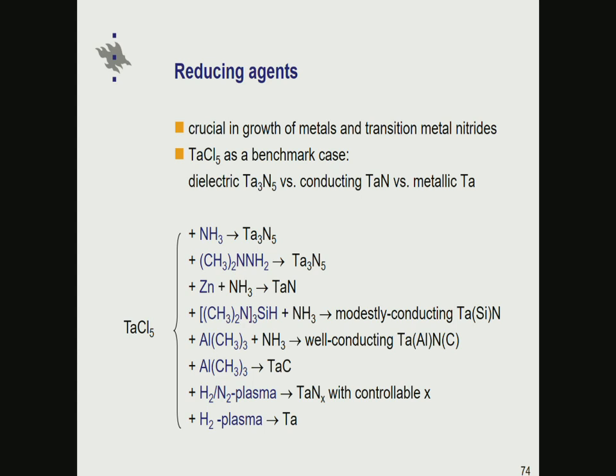Then reducing agents. This is of course something we need when we want to deposit elemental films. And well, we had the lucky unique case of antimony earlier, but here I like to use tantalum as an example, because tantalum exhibits different oxidation states in its various compounds. So starting from tantalum pentachloride, of course tantalum is +5. Now using nitrogen precursors, one can end up either having dielectric Ta3N5, so this is still +5, or conductive, normally tantalum +3, or one can go all the way to metallic tantalum.